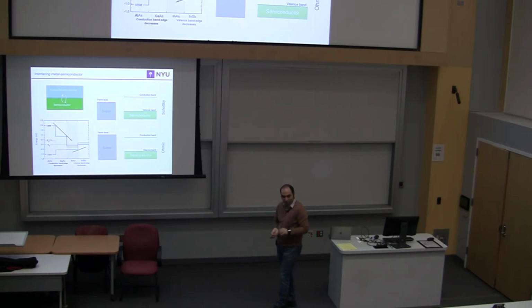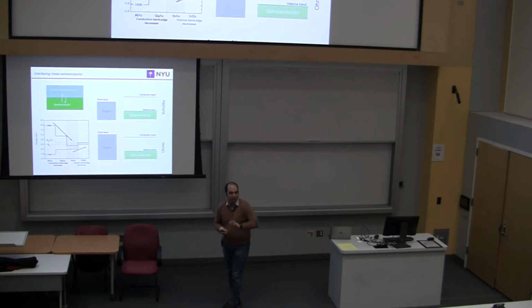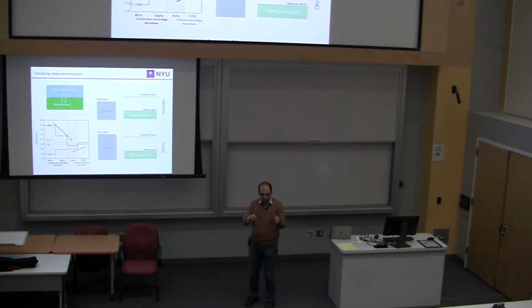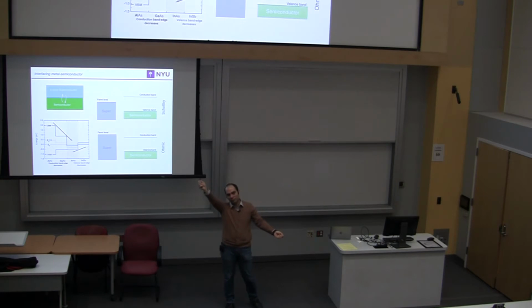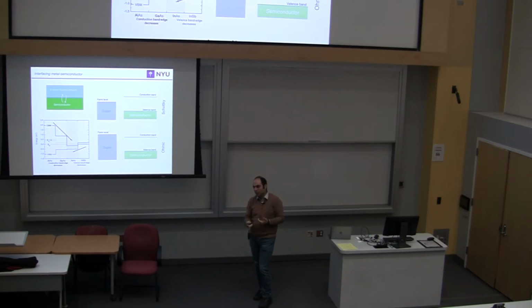So there is the crossing. Gallium arsenide is a Schottky barrier, right? You see this is the Fermi level, the pinning. This is the band gaps, right? Here we have Schottky barrier, indium arsenide, we have ohmic. So there must be a crossing, right? If I plot InGaAs as a function of the Fermi pinning, at the beginning I'm in the gap, and then at some point I cross the conduction band, and then I become pinned in the conduction band. So that crossing point is x of 0.85, right?